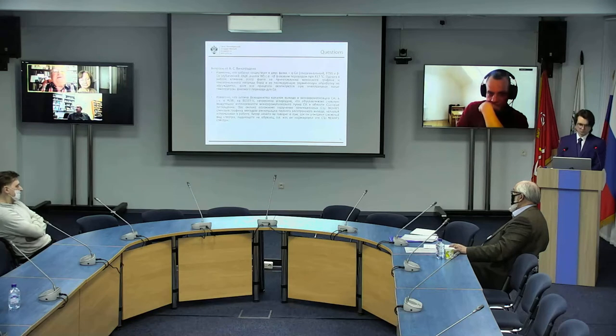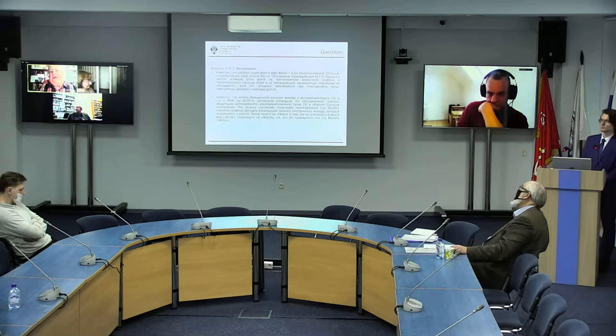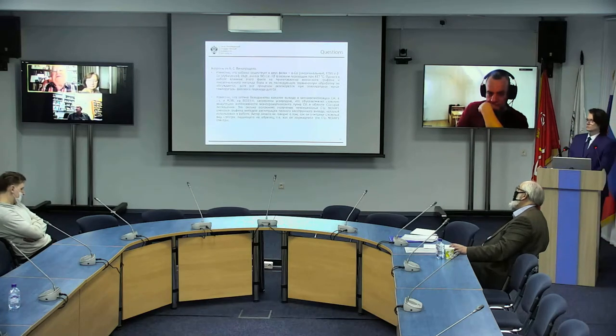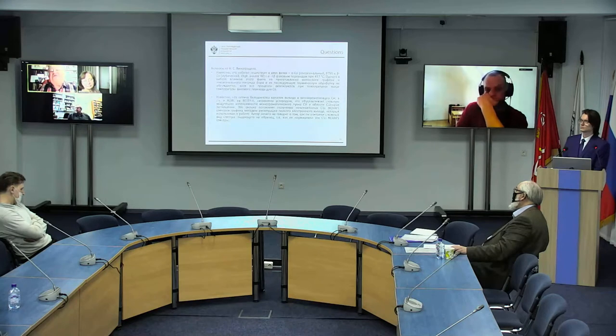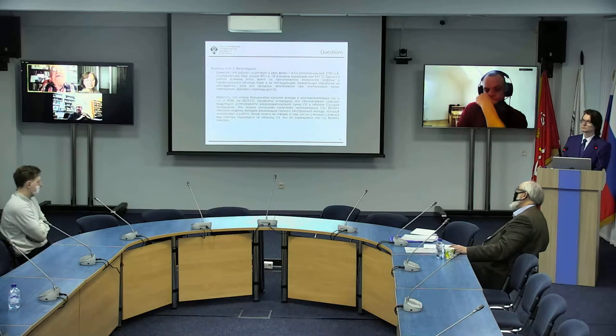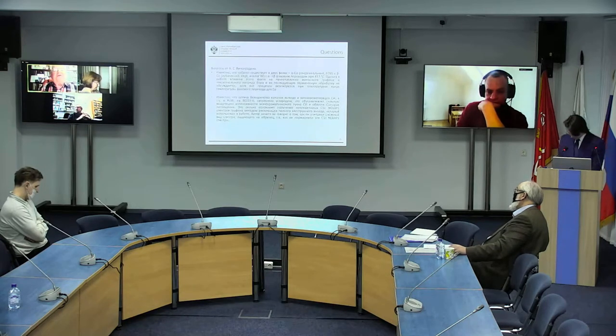That's the first point. Second point, we know that the optics of the majority of extraction channels and monochromatization is polluted by carbon, and this explains the strong modulation of intensity of the monochromatic beam in the area of the C1s absorption edge. This complicates acquiring a non-distorted spectrum for graphene if we use the method of registering the full electron yield, which is further complicated by the low contrast of this monolayer's spectrum. And you don't talk about how you account for this complicated type of spectrum, so how do you normalize this C1s spectrum?